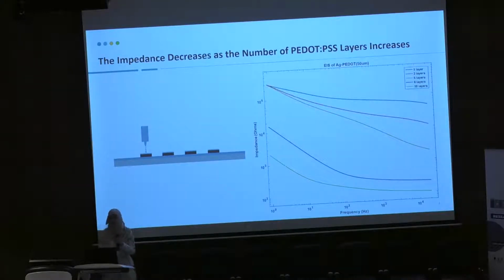To solve this problem, we modify the surface of the electrode by introducing materials that enhance the roughness of the electrode, or we use materials that have electrochemical means which enhance the performance of the electrode. In our work, we target both the chemical and topographical approach by depositing layers of a biocompatible polymer called PEDOT:PSS. So this material is commonly used, and here in our work, we showed how different layers of PEDOT:PSS will drop the impedance.